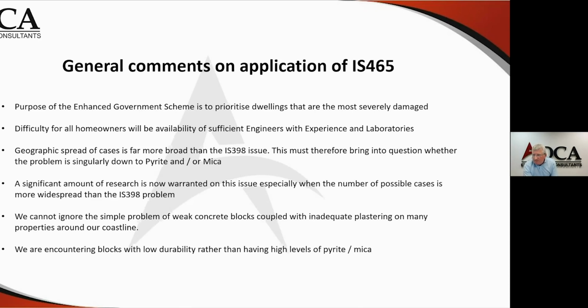are going to be overly exposed to moisture, to wetting and drying cycles, which some research recently has been showing gives deterioration of a concrete block on its own, regardless of whether it has any pyrite or mica within it. A standard 5 Newton concrete block has a relatively low level of cement within it. And with a large number of wetting and drying cycles, you can end up creating degradation of the concrete block in a similar way to mica, etc.